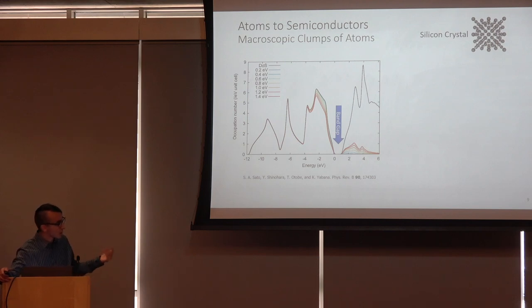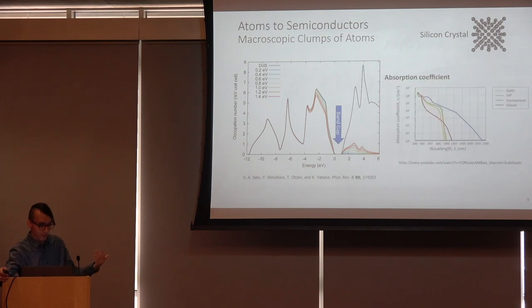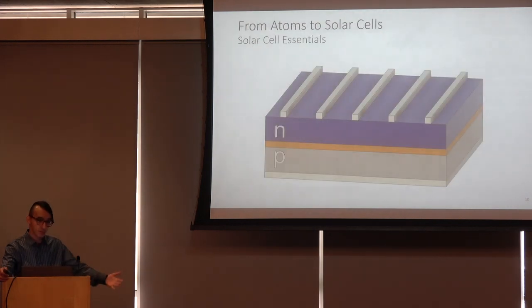And as soon as we turn on the temperature, electrons start gaining enough energy to hop across that transition, and you start getting some empty states in the valence band called holes, and you start getting conduction band electrons across the band gap. However, you can also give the electrons enough energy to make that transition optically, as with the hydrogen atom. And so if we look at the absorption coefficient of silicon in red on the right there, the point at which it crosses the x-axis there is essentially the same energy associated with the band gap transition, 1.1 electron volts. And so now we're ready to actually build a solar cell.